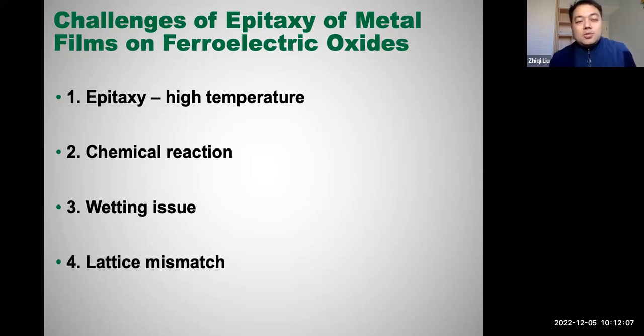But the growth of metal on oxides could be really challenging. For example, you first need a high temperature to have enough thermal energy to let the atoms of metals go to their equilibrium sites. But when you try to do deposition at high temperatures, the chemical reaction between oxides and the chemically reactive metals would be significant. And then you would have an interfacial oxidation layer or a secondary alloying layer that will easily destroy the epitaxy.